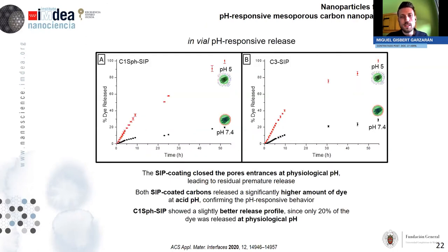Okay, so after functionalizing and characterizing the nanomaterials, we carried out again a release experiment, again using physiological pH and acid pH to mimic the pH of the lysosomes of the cells. And again, as you can observe, in the absence of acid pH, the polymers could block the release, so they were effectively closing the mesopores. But at acid pH, again, we could see a very drastic release. So this means that we can translate the stimuli-responsive technology from silicon nanoparticles to carbon nanoparticles without losing any of the functionality.